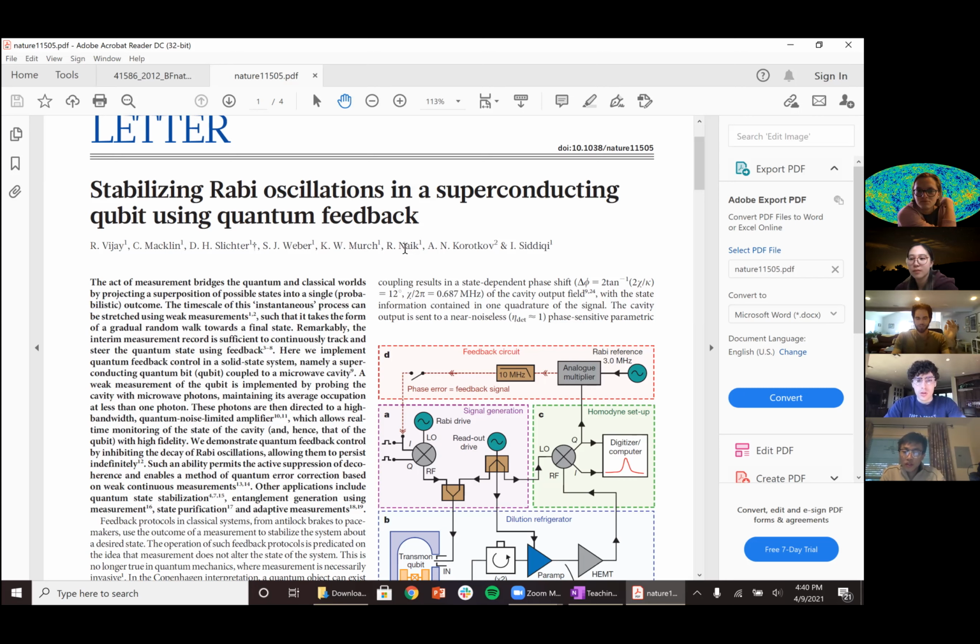Anyway, for some superconductors, we have a pretty good theory for how this happens. And that tells us how, for instance, aluminum becomes superconducting. This circuit was made of aluminum. It becomes a superconductor below about 1 Kelvin, so it has to be pretty cold. But there's this whole other set of superconductors that are called unconventional, where basically we don't know why they superconduct. The well-studied theory of superconductivity doesn't explain how you get this pairing of electrons.